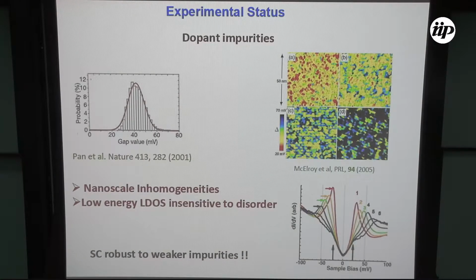So what is the experimental status on the impurity effect? If you look at STM, the gap map in the sample, red is low, so there are some places which are low in gap, and some places which are high in gap. The gap map shows that there are nanoscale inhomogeneities in the sample, and that persists for all dopings. If you plot the distribution of this gap, you will see that it's a Gaussian distribution like this.